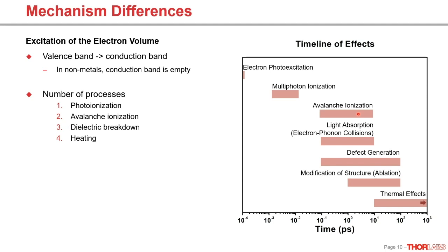So in the ultrafast regime, that is the pico and the femtosecond processes, you're going to worry about photoionization and avalanche ionization. In the nanosecond regime, most of the damage is typically going to be caused by dielectric breakdown. And then finally, in the CW regime, you are going to see heating. And for longer pulse trains, you can see heating contribute to any of these. But typically when you're getting the results quickly, it's going to go in that order.